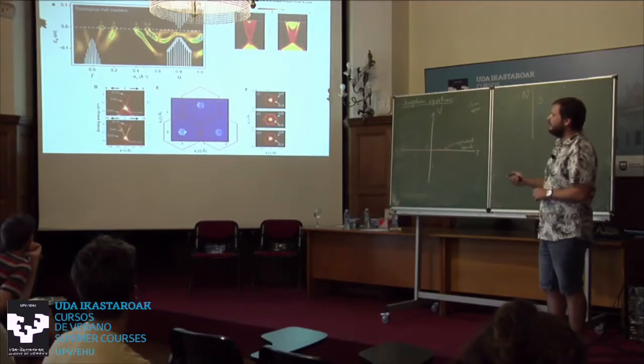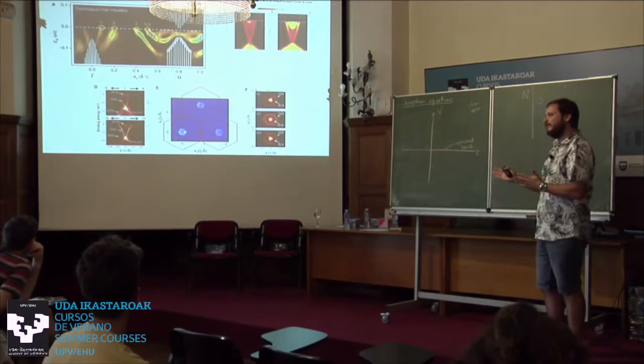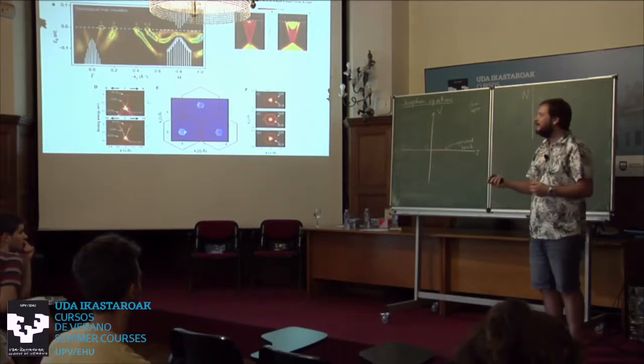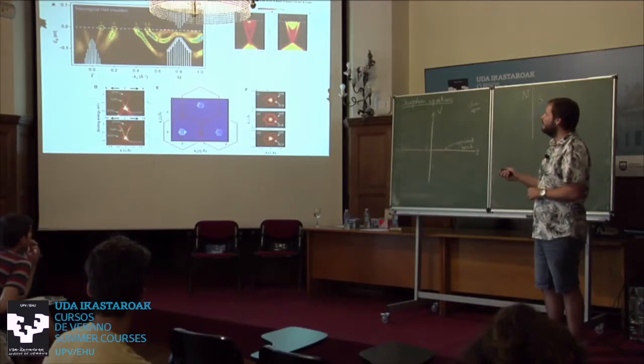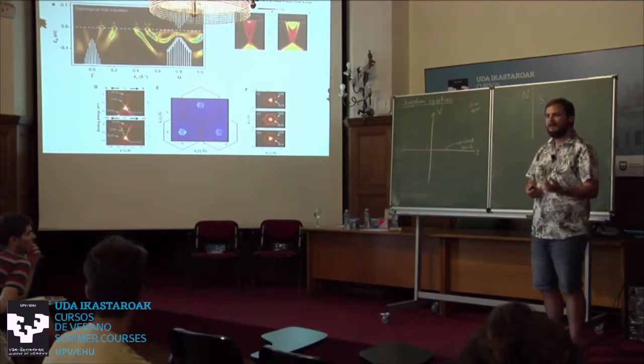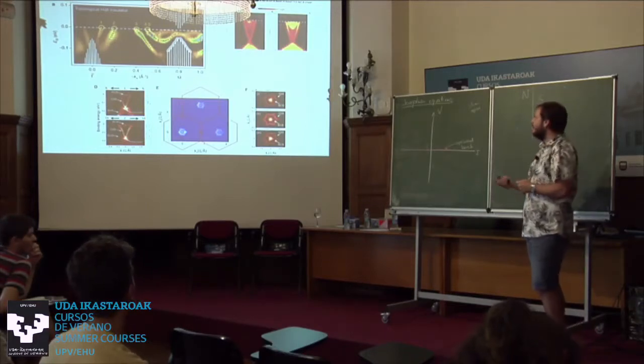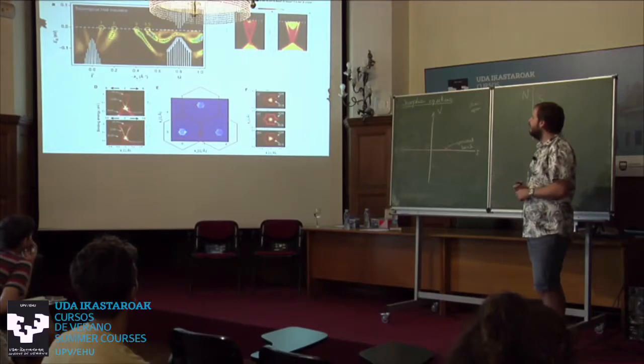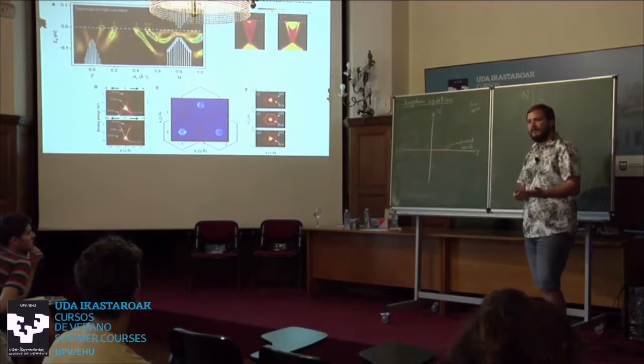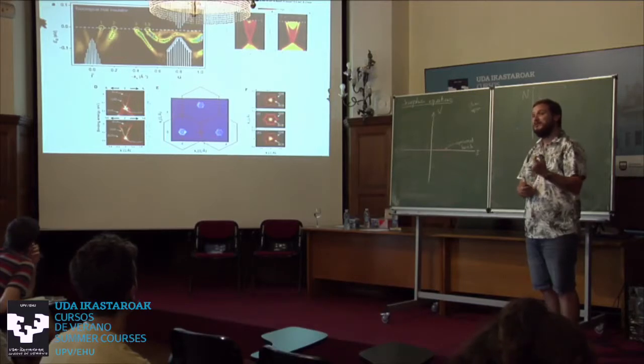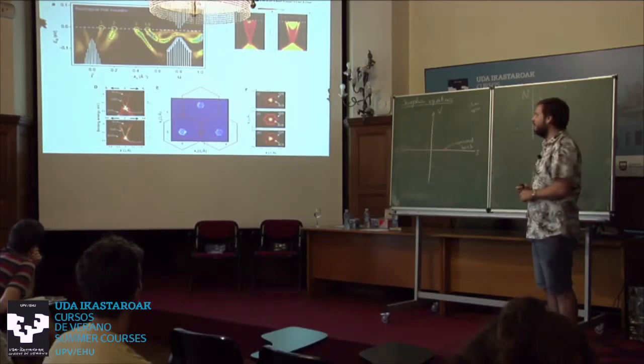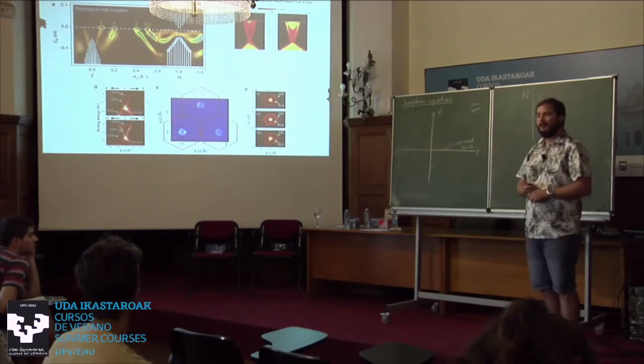This was the first observation. The first material was a bit too complicated — five surface bands summing to an odd number. Then came the more canonical topological insulators with a single surface band: bismuth selenide and bismuth telluride. This surface band was visualized, and its spin texture was visualized in spin-ARPES. This seems like a valid identification of unique surface states that classifies these materials as topological insulators.